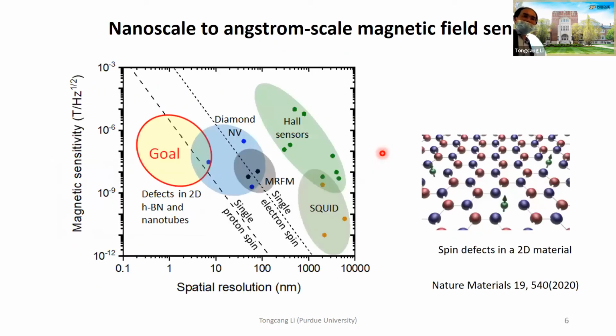Another one is magnetic field sensing. Diamond emission can give you pretty good sensitivity of magnetic field, with a resolution of typically tens of nanometers. But if we use 2D material, you can put a monolayer 2D material on top of the material you are interested in. So in principle, you may be able to reduce this separation to 1 angstrom. So there's a chance towards angstrom scale magnetic field sensing.